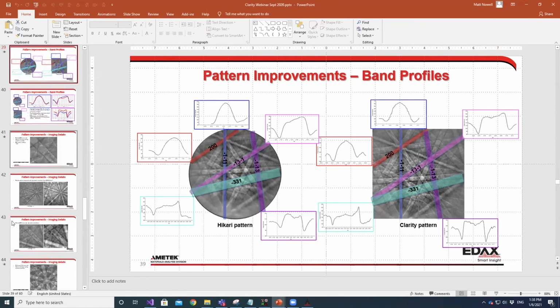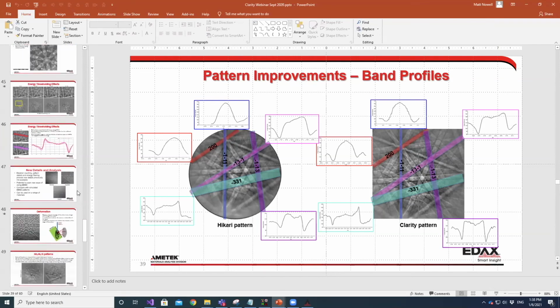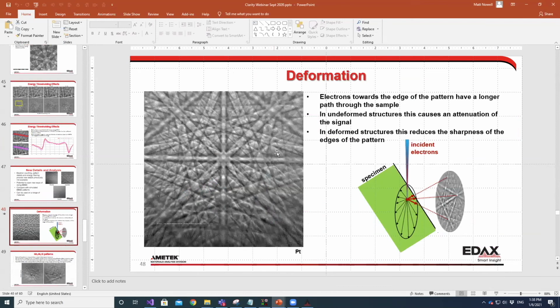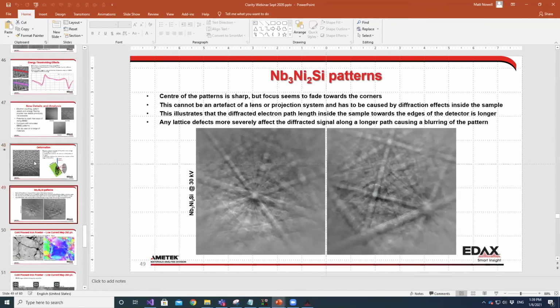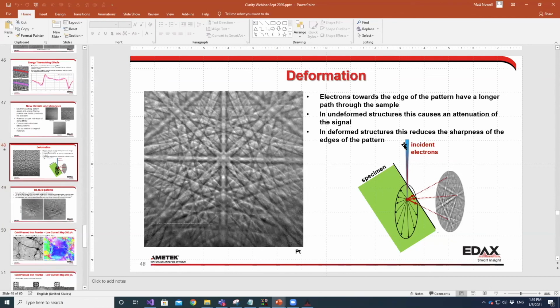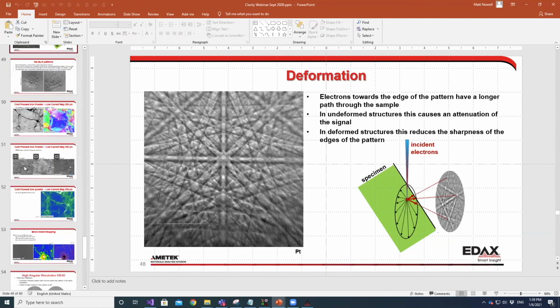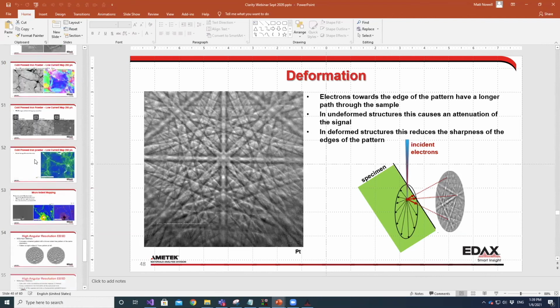And there's things that are just like, let me see, this is an interesting one here, where if we see that the pattern starts to become more diffuse at the edge, we know that's not due to any lens artifacts. Now we know that's due to the electron beam passing through the material on the way to the surface, and it's interacting with whatever defect density is there. So the lack of sharpness comes from a higher defect density. So we can start to think about, can we correlate sharpness with that defect density as a metric of material quality from a single pattern.